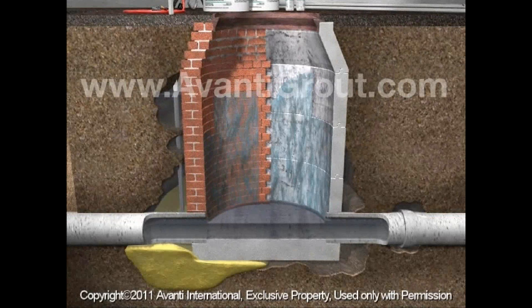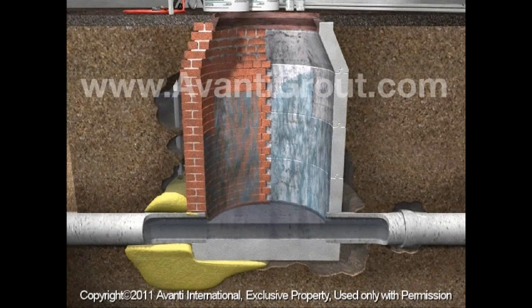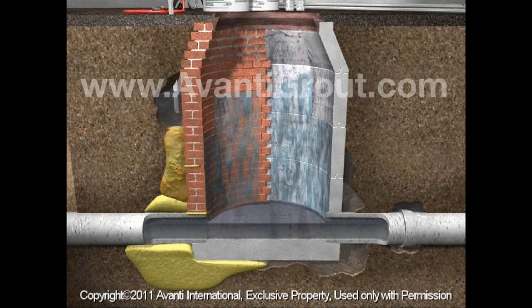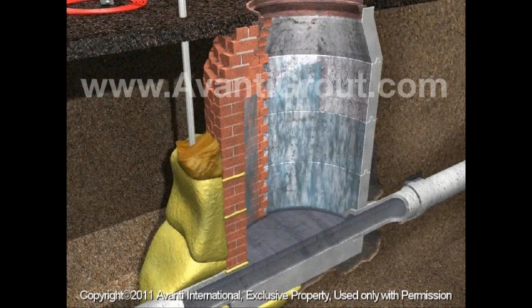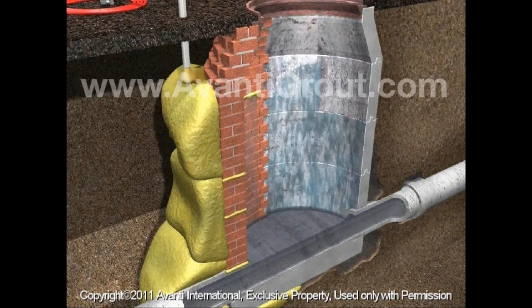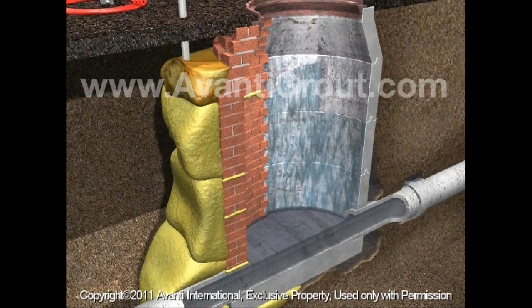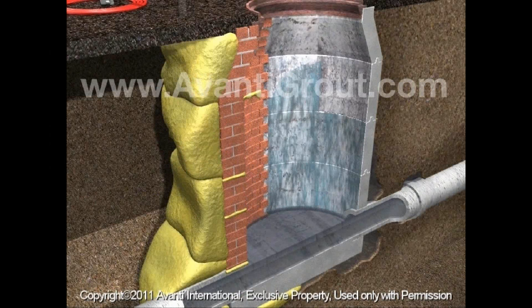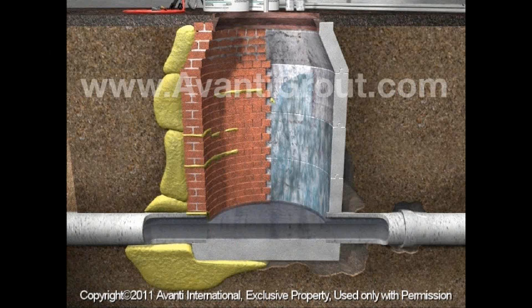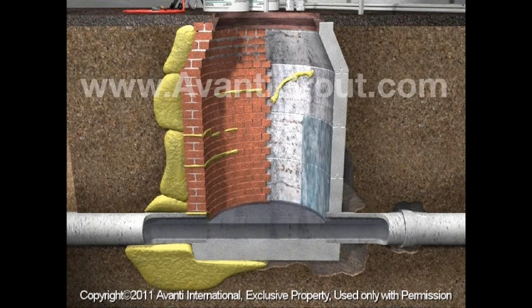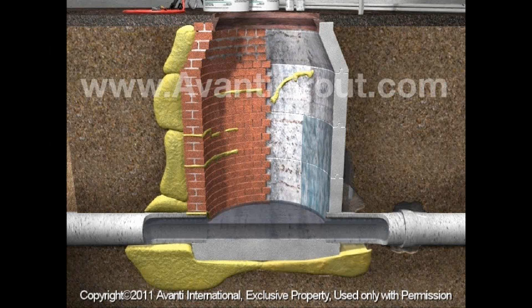The probe may be jetted with water pressure or high pressure air to the depth desired. Install all pipes in the area to be grouted. Ensure that the pipes are fitted with the appropriate fittings for a proper connection. Each injection pass will receive about 1/4 gallon of material depending on the soil type. After the desired amount of grout is injected, stop pumping and pull the probe up approximately 2 feet. Inject again using the same technique. Continue the process until the probe is within 3 to 5 feet of the surface of the ground.